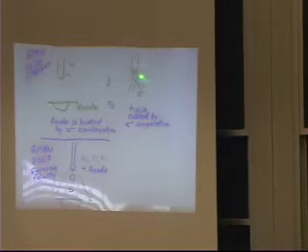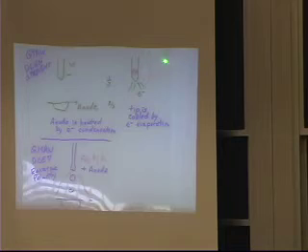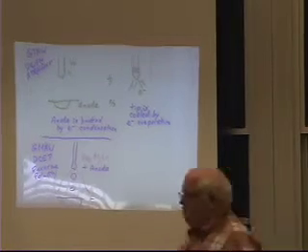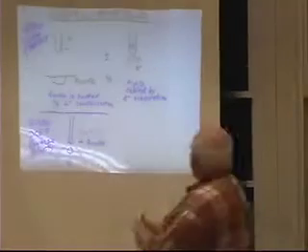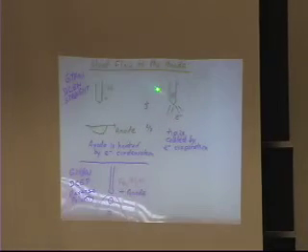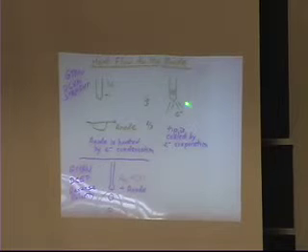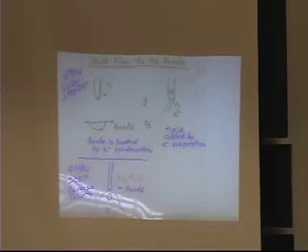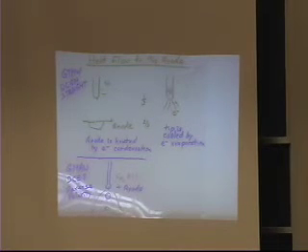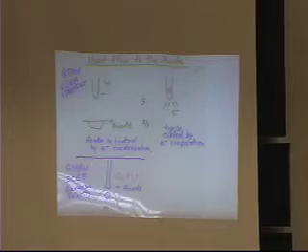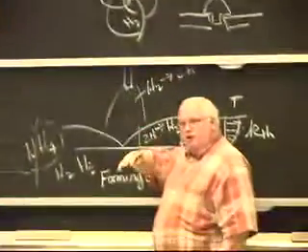And it turns out Professor Savage at RPI had a student a number of years ago who basically used infrared thermography, and actually this is supposed to be a little picture of temperature up here. You can hardly see it, it's in red. But he actually found the hottest part of the tungsten electrode was not right at the tip, but just back a little bit, because the electrons coming out are taking the work function heat, which is the energy from the Fermi energy up.